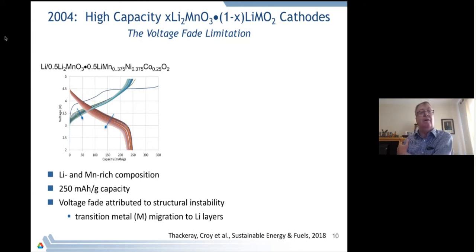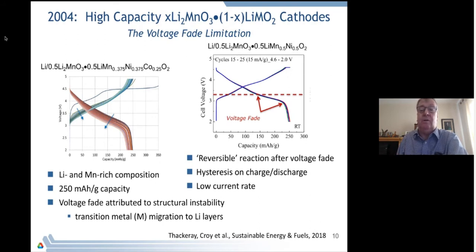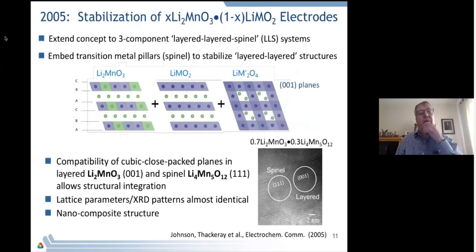It was Jeff Dahn who first pointed out that if you took these materials and charged them above 4.5 or 4.6 volts, you could strip lithium and oxygen out of the structure and increase the capacity of the material considerably, to get capacities of about 250 milliamp hours per gram. Unfortunately, these materials suffer from voltage fade, which is attributed to structural instability and particularly the migration of transition metals into the lithium layers. But if you control the reactions and narrow the voltage window, you can actually get very good cycling performance from some of these materials. They only operate really well at low current rates, and there is some hysteresis on charge and discharge, which doesn't count in its favor as regarding power output. So there were these problems associated with these layered materials, and we're still working on them at Argonne.